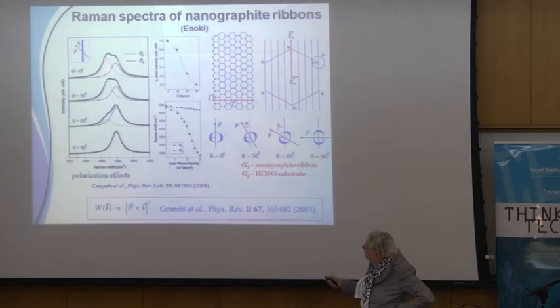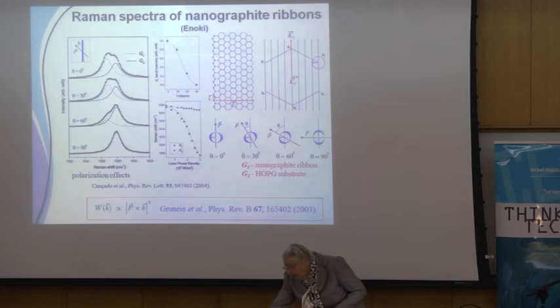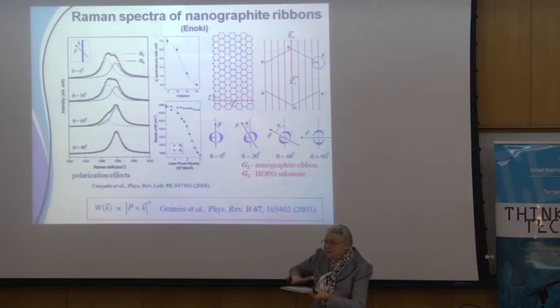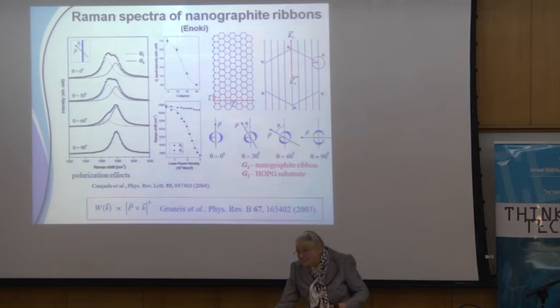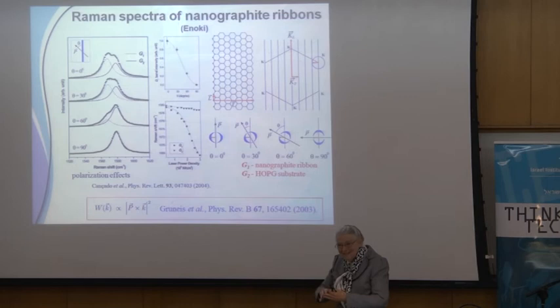It's all the same hexagons, but when the laser hits the ribbon, it gets warm because the thermal conductivity in this direction is very poor. Thermal conductivity in this direction is huge. So the difference in conductivity is several orders of magnitude, almost 10 to the 3, a very big difference in thermal conductivity. So we can heat this little ribbon and change its frequency, so we can always distinguish the ribbon from the substrate. That's the trick in this experiment.